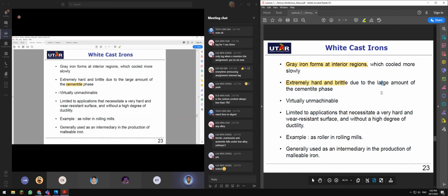These white cast irons are virtually unmachinable because they are very hard and have very high wear resistance. White cast irons are limited to applications that necessitate a very hard and wear resistant surface without a high degree of ductility. It has a very low degree of ductility. For example, you can use white cast iron as a roller in rolling mills. Remember rolling mills, the video that I shared with you last time, where it shrinks hot work material from bigger diameter to smaller diameter. Generally, it is also used as an intermediary in the production of malleable iron.